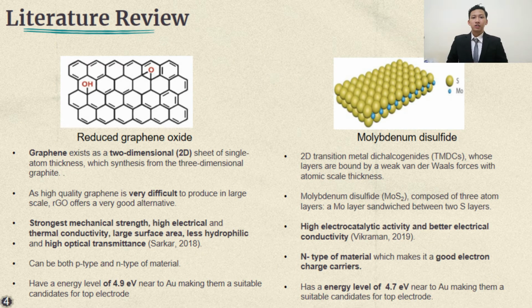Moving on to the literature review section, graphene exists as a two-dimensional sheet of single atom thickness, which is synthesized from the three-dimensional graphite. As high-quality graphene is very difficult to produce on a large scale, reduced graphene oxide offers a very good alternative, as it possesses strong mechanical strength, high electrical and thermal conductivity, large surface area, less hydrophilic, and high optical transmittance. This material can be either P-type or N-type, and it has an energy level of 4.9 eV near to Au, making it a suitable candidate for top electrodes.